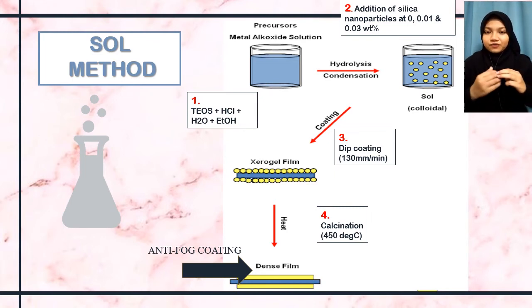After being aged for a few days, the glass slide is dip coated in the solution. In order to have hydrophilic properties, the glass slide is heated up to 450 degrees Celsius and a dense thin film is obtained. The thin film is known as an antifogging coating.